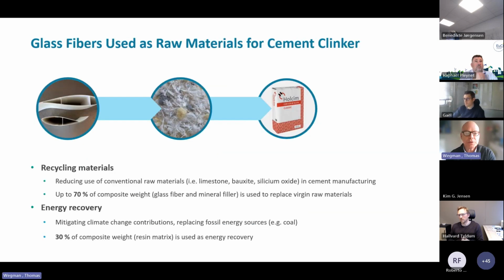When we talk about cement co-processing, just to be very clear on what it means, it does not mean that we're going to take the fibers and reinforce concrete. That's not co-processing. Co-processing is taking the composite material, grinding it and using the full composition for making the cement. The material is heated up to 1400 degrees, which means that the fiber shape is lost and that the ingredients in the material are going to be used as raw materials for making cement, up to 70% of the composite weight, depending on the specific composite part composition.